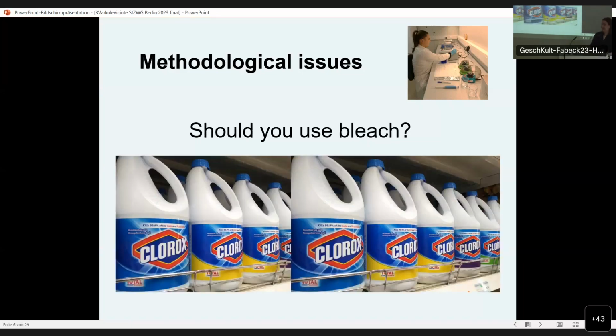Another big question, bleach. While it is usually used as a first step to remove organics from the enamel, which in archaeological enamel, it is questionable how much there is of it. There are also several studies that show that using bleach can facilitate absorption of exogenous carbon, potentially from the atmospheric carbon. And it is a big problem if we want to preserve the values.